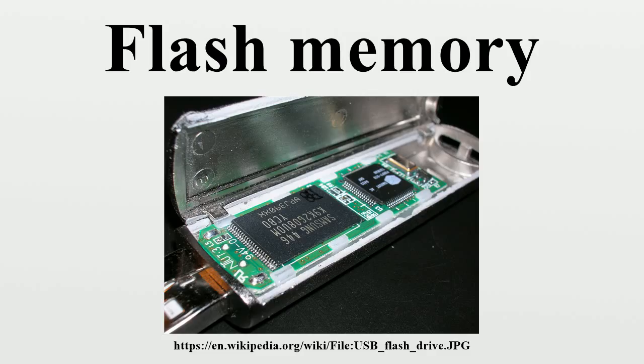Vertical NAND uses a charge trap flash geometry that stores charge on an embedded silicon nitride film. Such a film is more robust against point defects and can be made thicker to hold larger numbers of electrons. It wraps a planar charge trap cell into a cylindrical form. An individual memory cell is made up of one planar polysilicon layer containing a hole filled by multiple, concentric vertical cylinders. The hole's polysilicon surface acts as the gate electrode.